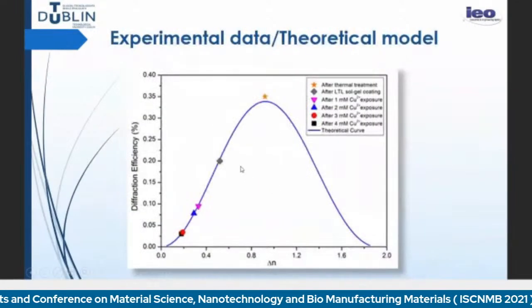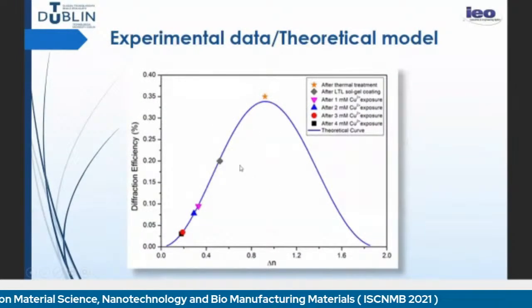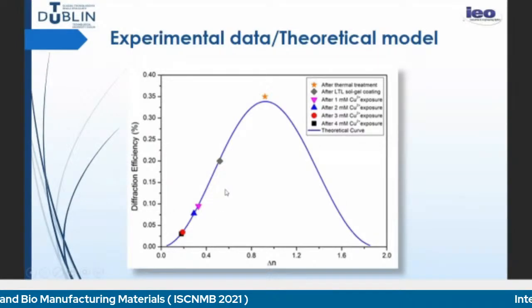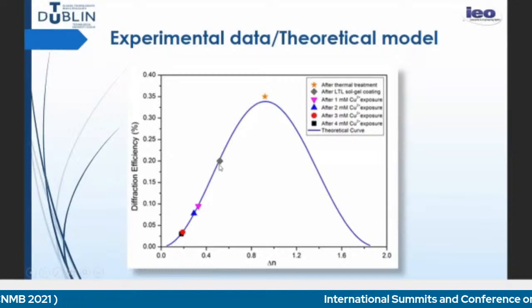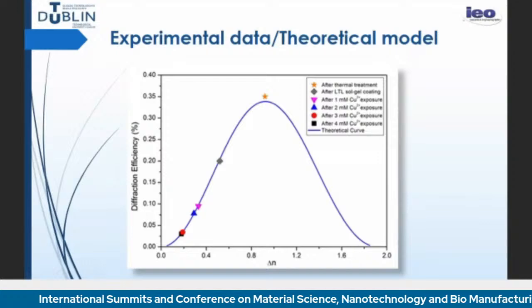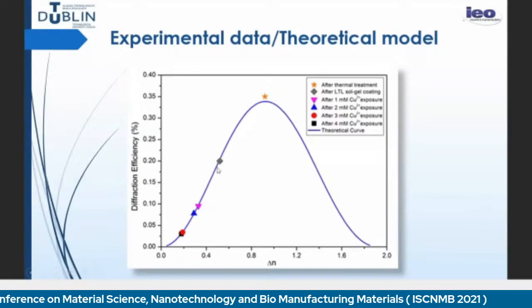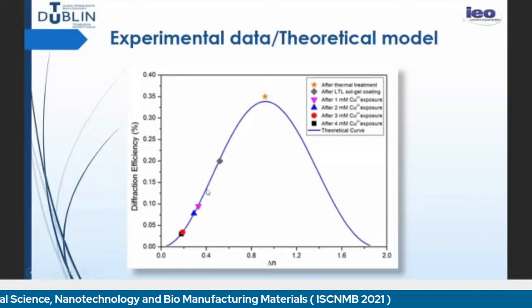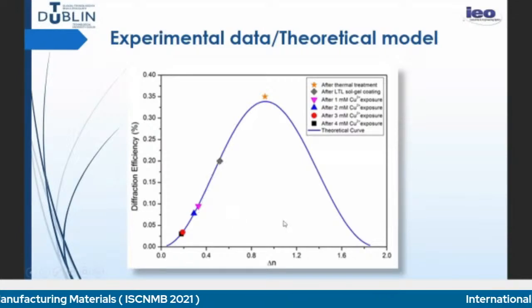And you can see here, this is after the thermal treatment. This is after the coating with the sol-gel. This is a theoretical curve of the diffraction efficiency. And this gap here is between just before exposure to the 1 millimole of copper and the exposure to 1 millimole of copper. So we are now focusing on exploring this gap, because this first step is quite large and implies that we should be able to achieve even better sensitivity of the layer.